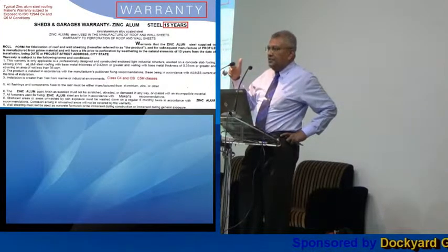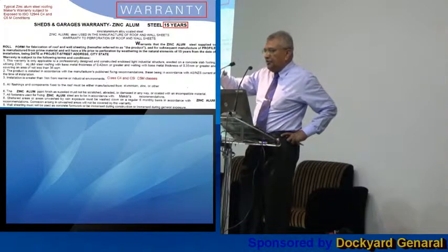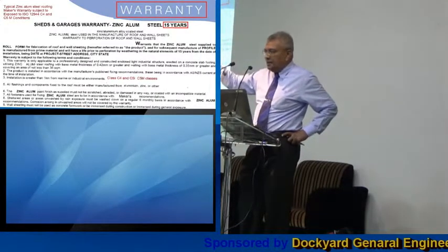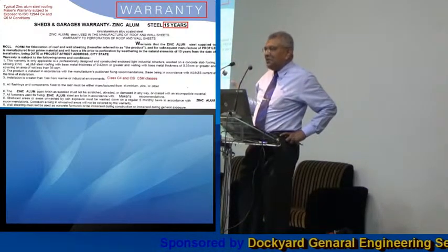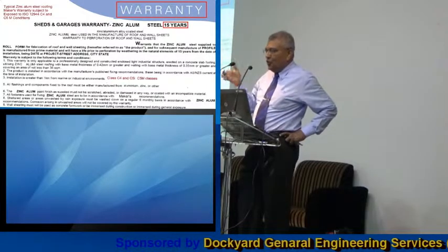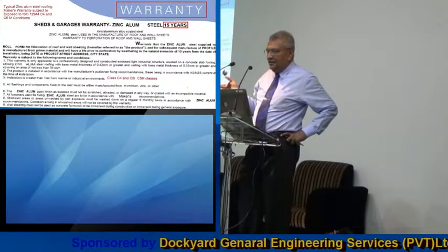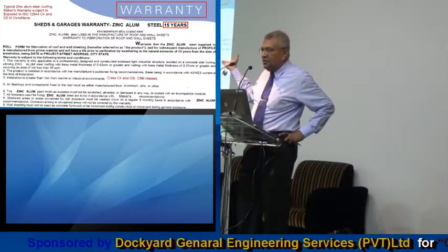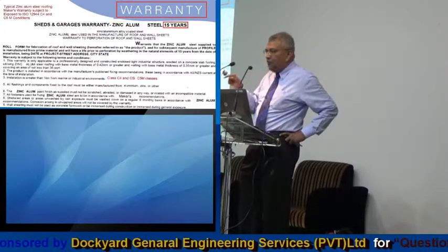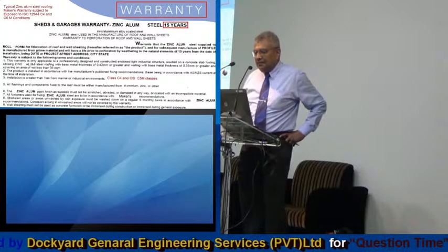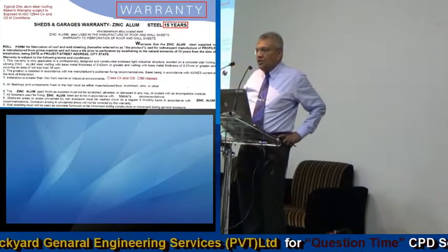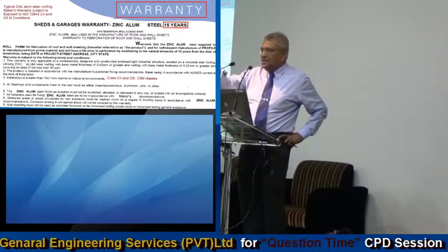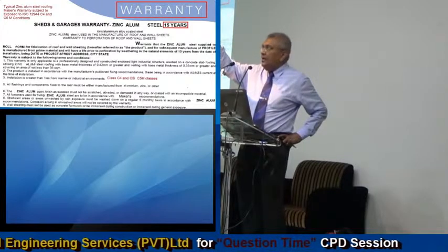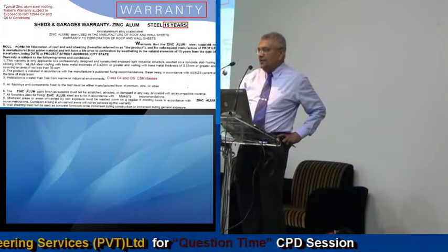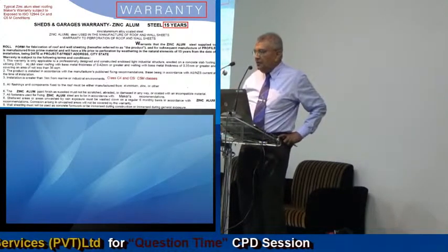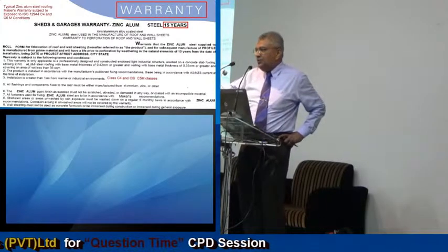But sometimes you will go and ask the contractor, give a 15-year warranty for this zinc aluminum sheet in the CX. It's a very unreasonable request. If you know your ISO, Eurocode, you will never request for the warranty. Because you can't request, the manufacturer doesn't give you his warranty. He's excluding the 1 kilometer from the seaside. Because it's sea breeze. And if you fix something in the petroleum corporation, you find those fumes are going up, the sulfur dioxide is burning, sulfuric acid will happen, and acid rain will fall. Acid rain is electrolyte. So it will corrode, it will sacrifice the zinc alloy. Then after that the base metal will corrode.